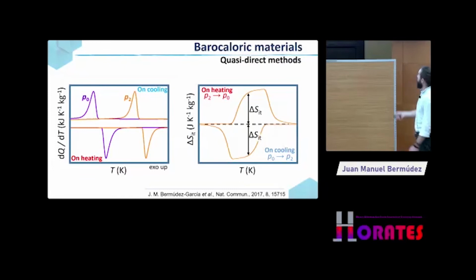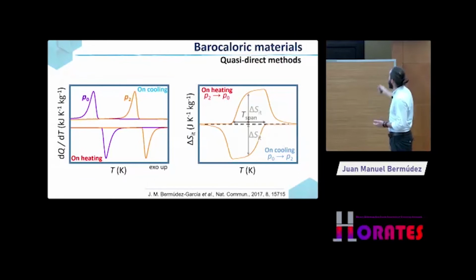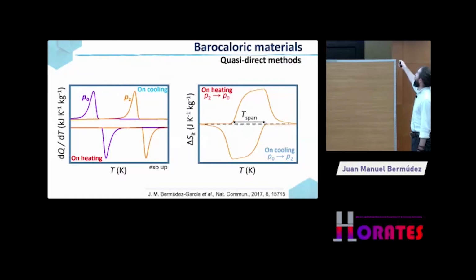So from here, we obtain the maximum value of the barocaloric effects that we can use for cooling at different temperatures. And this temperature range over here is the range in which your material exhibits barocaloric effects. So that will be your temperature span or the operating temperature range for your material. So your material can work in all this range of temperatures, because if you go over here, you cannot recover the heat. If you go over here, you don't have a caloric effect either. So your material can only work here.